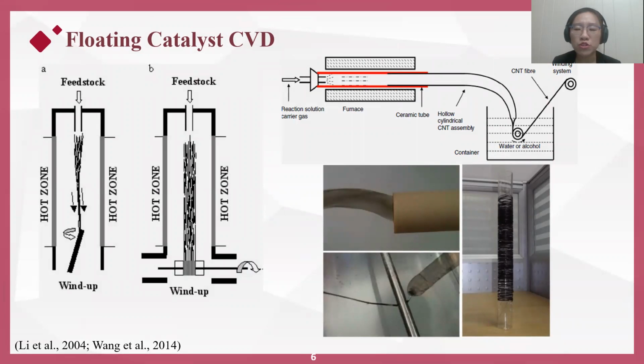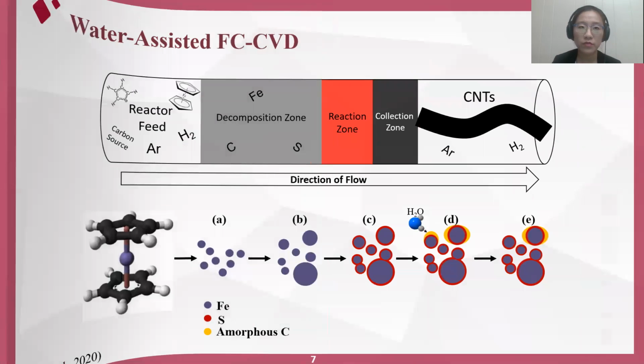While the conventional substrate-based CVD tunes the nanotube diameters by precisely controlling the catalyst sizes, the significant batch-to-batch variations remain a big drawback. On the other hand, with a continuous catalyst feed and controlled synthesis conditions, the floating catalyst chemical vapor deposition process is more suitable for mass production, and it could achieve flexibility in product forms, such as yarns or sheets, depending on how you would like to collect.